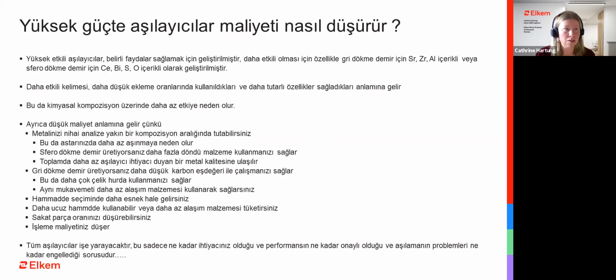There are some inoculants that are specially designed for gray iron, those that contain zirconium or strontium, or aluminium. In ductile iron, they will typically have cerium, bismuth, sulfur, and oxygen in order to be more effective. So these are inoculants designed to work specifically for that need. For gray iron, working only with strontium and zirconium, you often have a very clean inoculant. They come with low calcium and in some cases also low aluminium. But too low aluminium in gray iron is also not recommended, as aluminium is an important part of the nucleation sites.